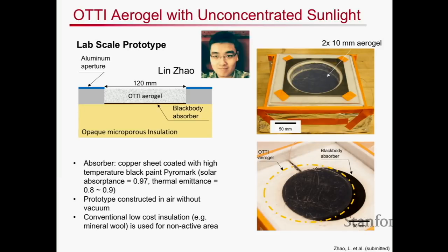So with this kind of concept, one of my students, Lynn, while it's been certainly a large group effort on our both Gong, Chen, and my group's collaboration, we've been able to first start off taking advantage of these aerogel structures and look at what is the potential of these optically transparent thermally insulating aerogels, right, in terms of using a black body type surface and just putting the OTTI, the aerogel, on top of it and looking at what's the temperature that we can reach, right, with no concentration at all.